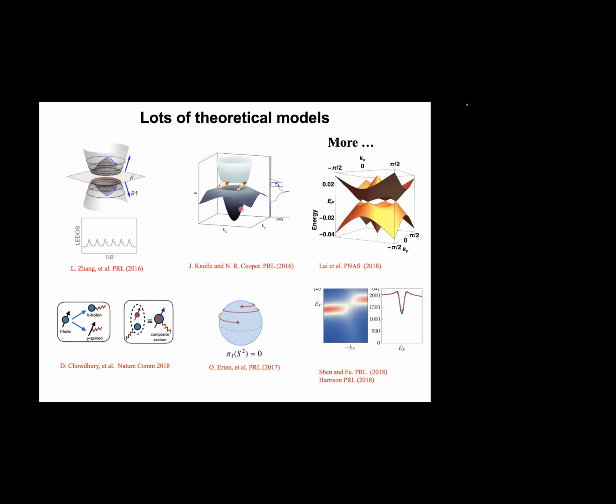There are many proposals coming out of this dilemma. When we see oscillations in an insulator, there's this very interesting exotic behavior, arguing from whether it's an exotic pattern like spinon Fermi surfaces or neutral superconductors, or something a little bit more conventional, when they argue something like disorder-driven states, or something in the topological states, whether it's coming from the free energy oscillations or coming from these states. There are many interesting proposals from theory.